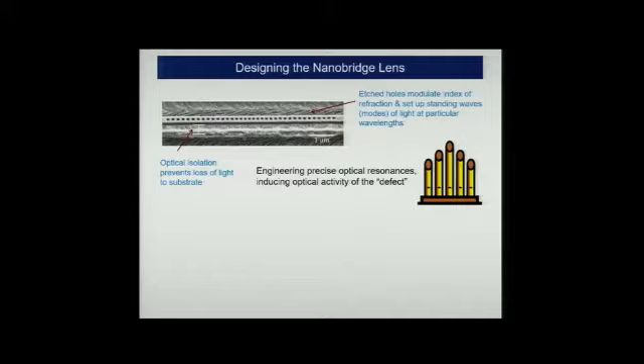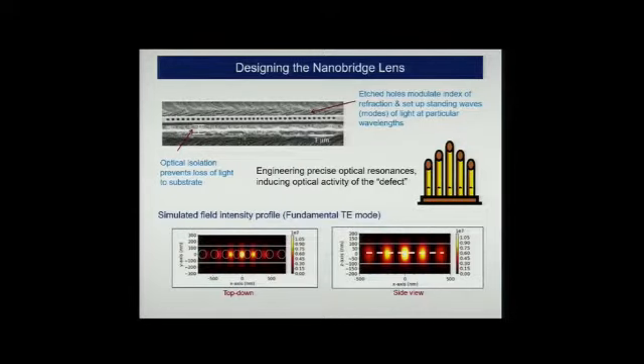The photons see a varying landscape of changing index of refraction. That varying landscape sets up, and I'll show you in a minute, standing wave stable solutions. Those standing wave stable solutions are the pure tones of this nanobridge. So we're looking for pure optical tones to match the optical emission of our silicon vacancies. But basically, this is a finely tuned instrument whose geometry determines the pure tones and the harmonics given by this nanobridge.